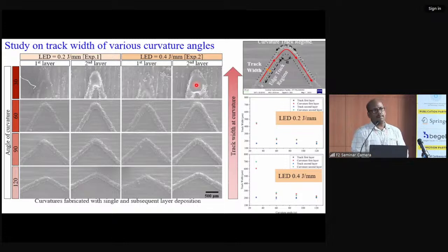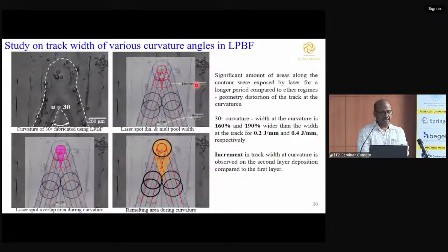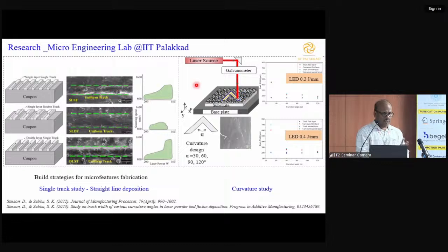How to optimize? There are many ways. One way is to optimize the laser power itself, adapting the power based on the requirement. But for that, we have to develop a machine in a different way. Out of these different angles, we found a problem in all of them, but the foremost problem is with 30 degrees, because the turn angle is very small, so a lot of material is deposited there. So from these two works, we are now able to make a proper track with the help of linear as well as curved optimization methods.